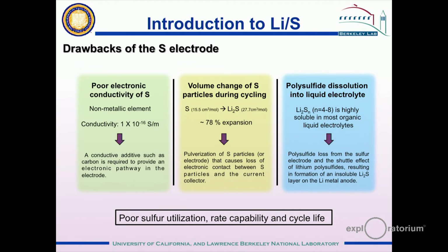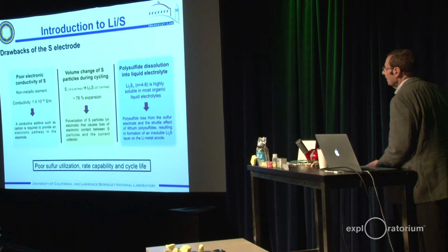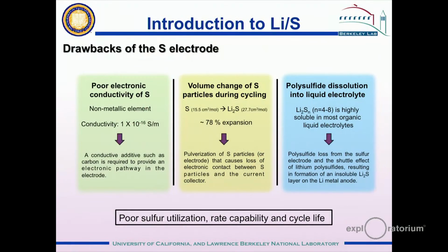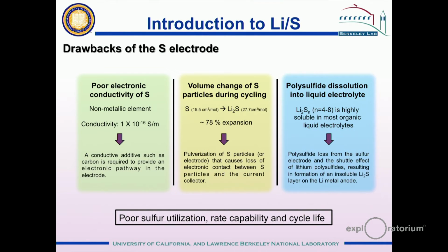Sulfur also changes volume as we discharge the cell. So we start out with sulfur, we discharge the cell making Li2S, and when we do that, the volume of the Li2S turns out to be much greater than the original volume of the sulfur, so we have about a 78% expansion. So our electrode has to accommodate that mechanical expansion. And we engineer our sulfur so that it is combined with carbon on a nanoscale, and we provide very good electronic conductivity by means of the carbon. And when we make the electrodes, we use an elastomer as a binder to accommodate the volume change.